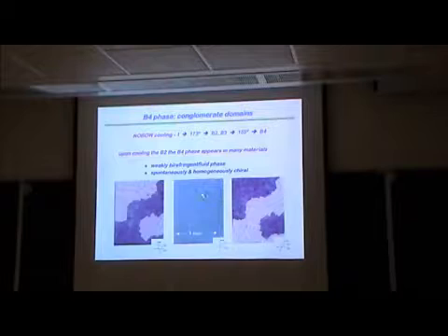So this is the same material, but now at a lower temperature. So you have a cell between cross polarizers. This is a cell that was cooled coming down in the phase sequence, so it goes into these fluid phases and then into what's called the B4 phase.